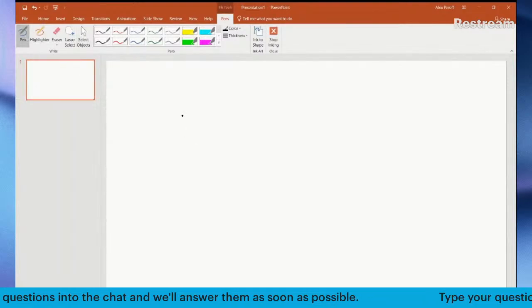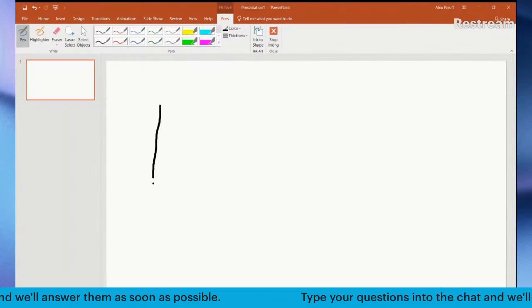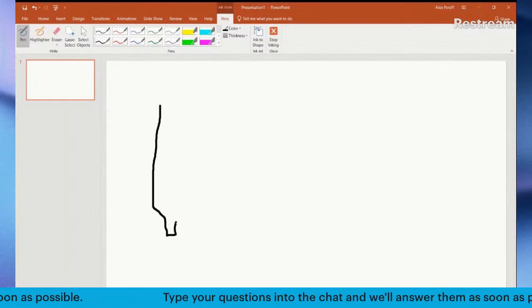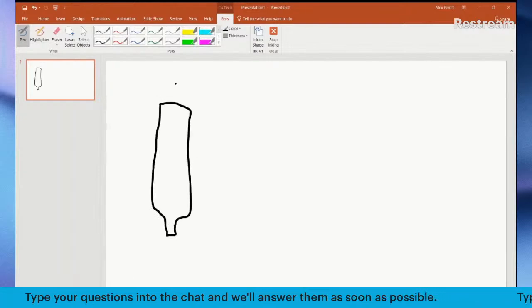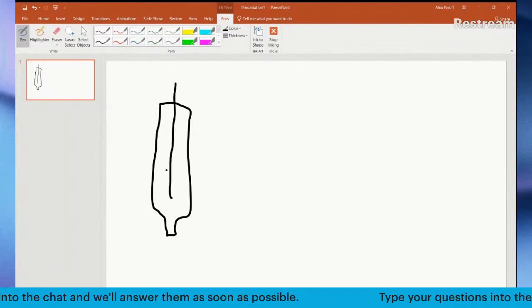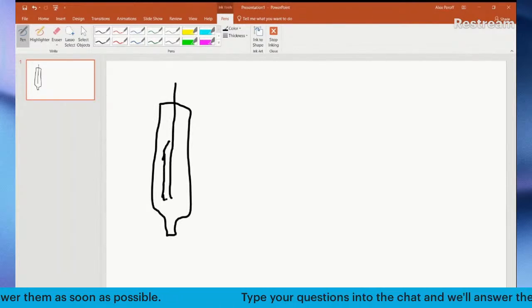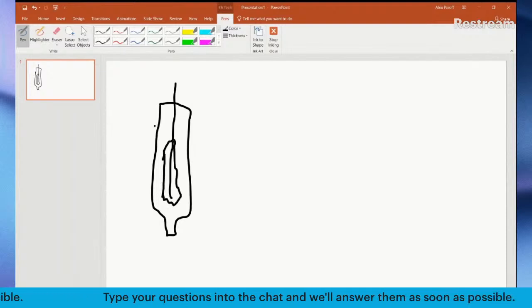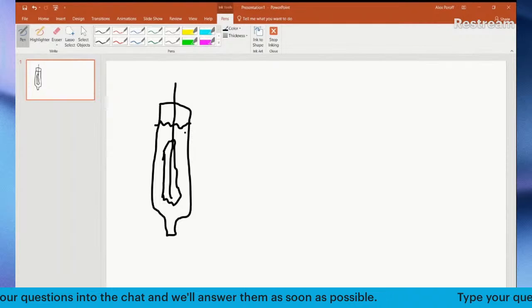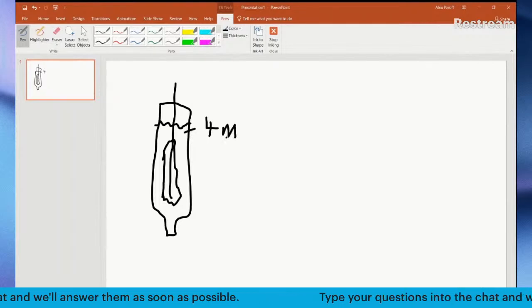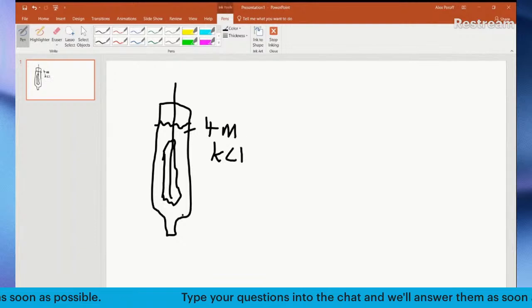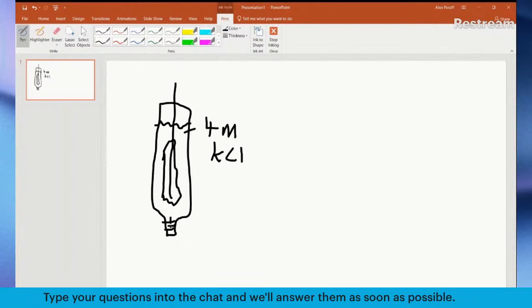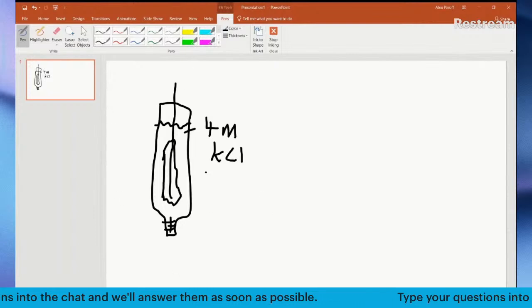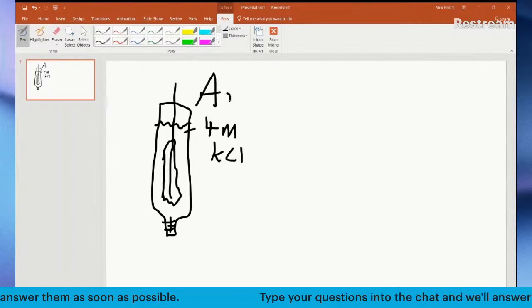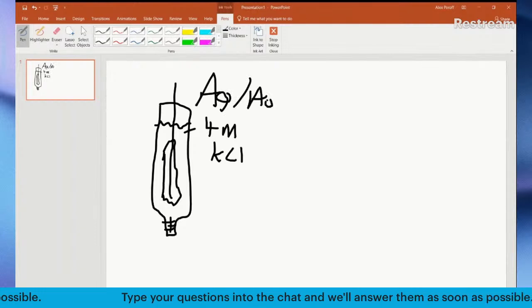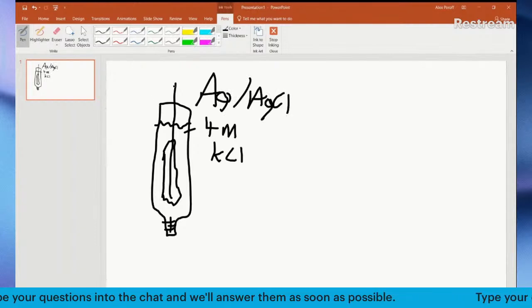So just to let people know, normally a reference electrode has this kind of construction where you have a fritted tube. There's a wire, like silver, and then there's silver chloride salt around it, and it's in a solution of, say, 4 molar KCl, saturated KCl. There's a frit here, and this is a normal AgCl reference electrode, and a reference electrode shunt.